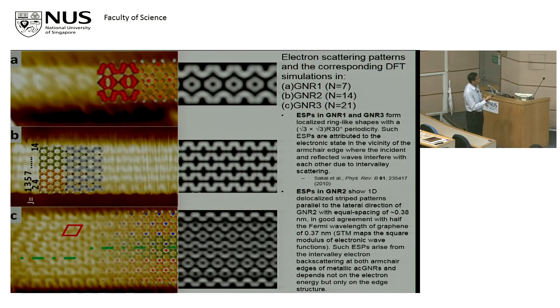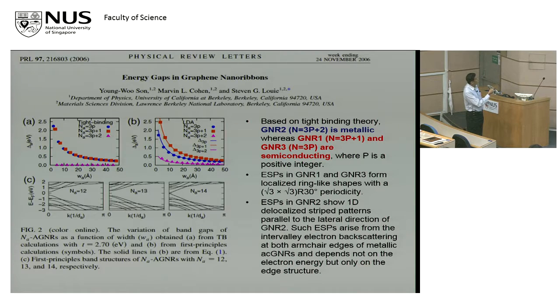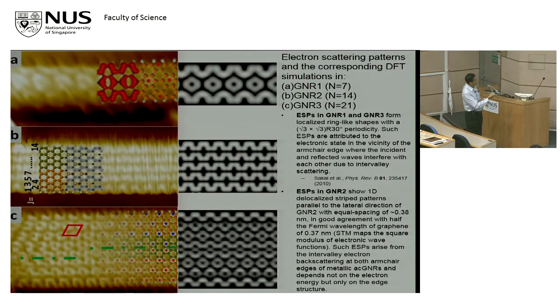And we tried to correlate it with theory, from Steven Louie's group, where they did theory and showed that at certain widths you get a band gap as the width gets smaller, but at certain widths you don't, either no band gap or a very small band gap. And those widths correspond to this kind of structure we observed.